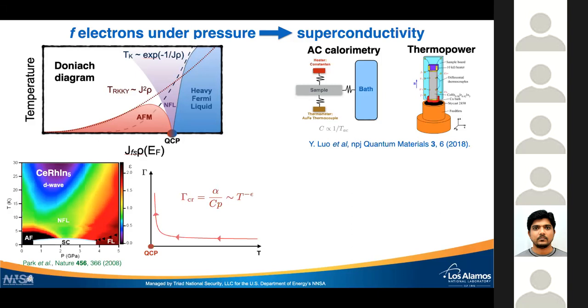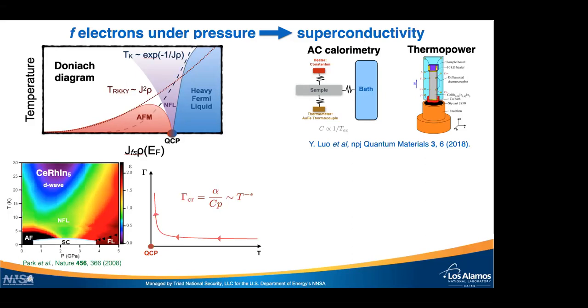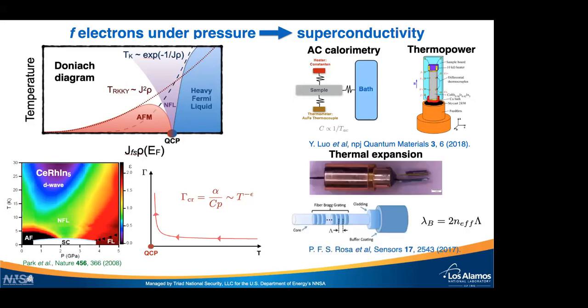So we know that the so-called Grüneisen parameter, which is the ratio between thermal expansion and heat capacity, diverges at a quantum critical point. But really, thermal expansion measurements under pressure are really challenging, and conventional capacitance dilatometers cannot be used. So very recently, we have been working on thermal expansion measurements using the optical fiber approach.